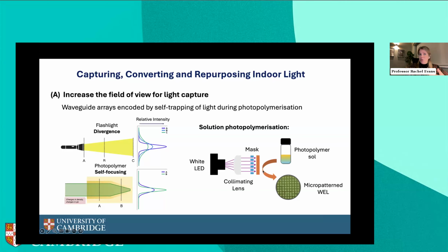Any part of the sample that's directly hit by the mask will polymerize first, and this is where the channels will form. And then by controlling the pattern of the mask and the orientation of the lenses, we can control the orientation of the waveguide channels that we embed within our material. So here in this case, we see a simple checkerboard pattern embedded into this polymeric film. So we have a way of capturing and transporting diffuse light.